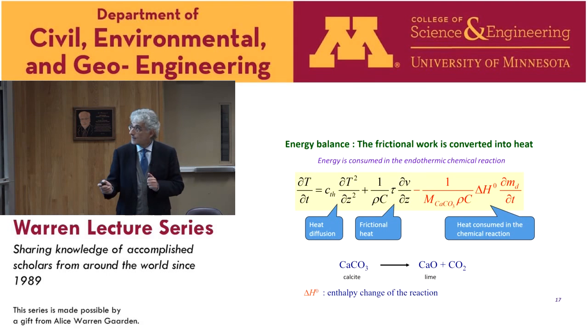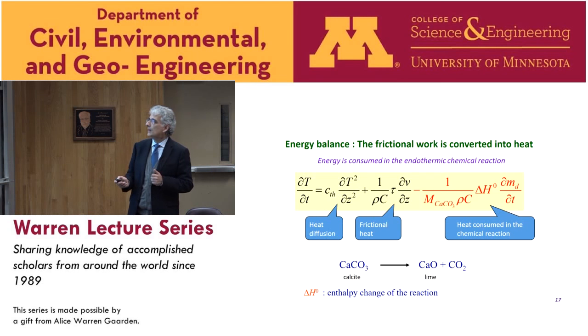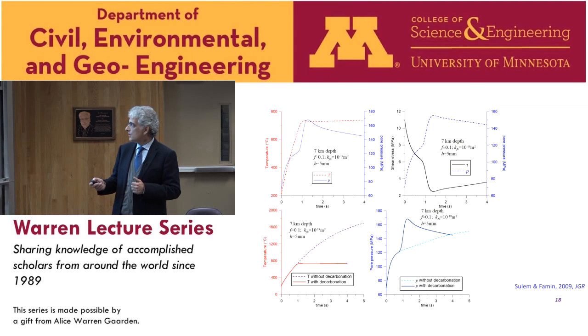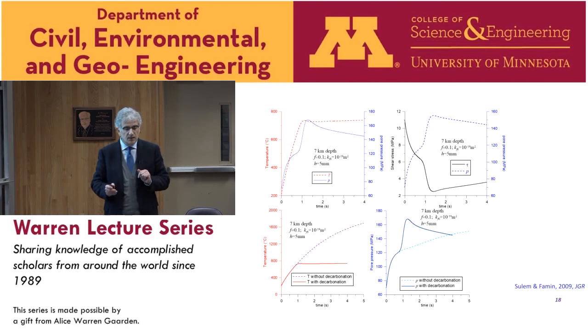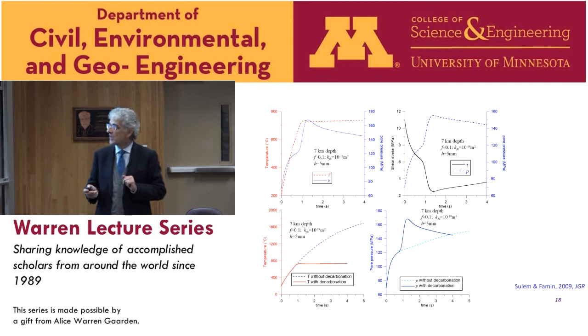We have the energy balance. We assume here that all the frictional work is converted into heat. So we recognize here the heat diffusion term, the source term, which is the frictional heat. And here with the sign minus, it is the heat consumed in the chemical reaction. And delta H naught is the enthalpy change of the reaction. So this is an example of computation. We consider a thin layer of 5 millimeters submitted to a slip of 1 meter per second.